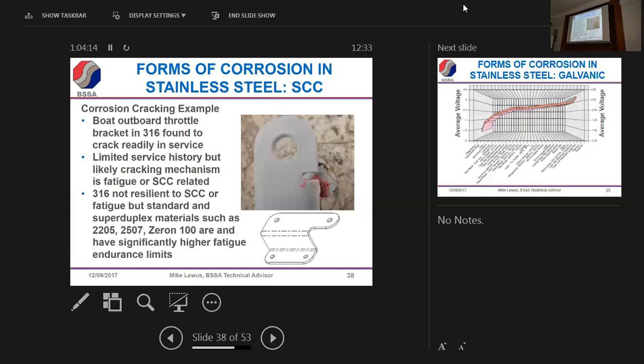And the guy said, well, what's causing this? We think it's fatigue or stress corrosion cracking. Now, there's only a few ways stainless steel can crack. It's either stress corrosion cracking, it's fatigue related, or the component is so overloaded that you've gone past the proof strength of the material, it's deforming, and you're either getting ductile or brittle failure that's opening up the material.